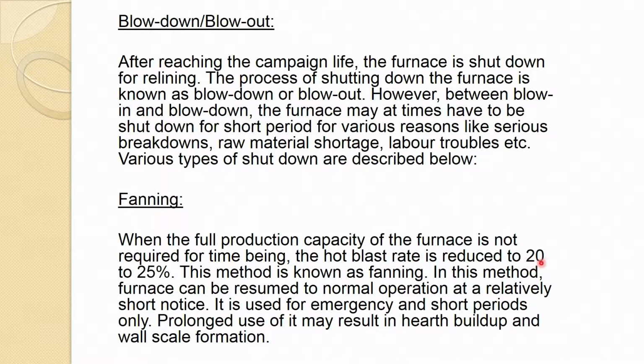So, one has to again reduce the capacity or production rate of the blast furnace. That is the time you take the hot blast rate by 20 to 25% out. This method is known as fanning. In this method, the furnace can be resumed to normal operation at a relatively short notice. It is used for emergency and short periods only. Prolonged use of it may result in hearth buildup and wall scale formation. So, this is for a very short period, used for emergency and other things. This is one of the ways you can reduce or blow down the furnace for a few hours.